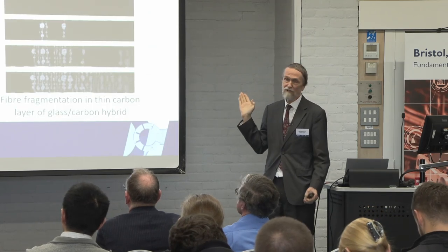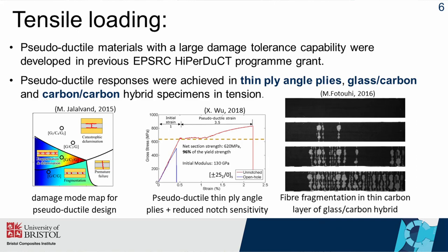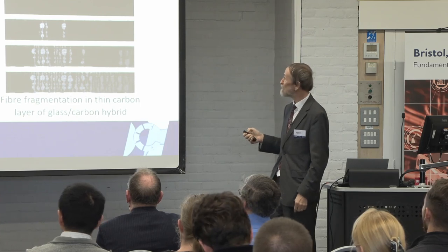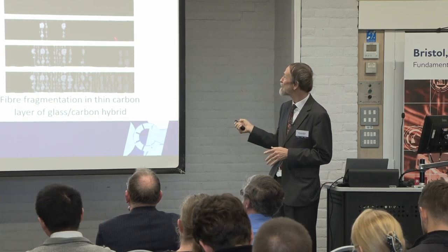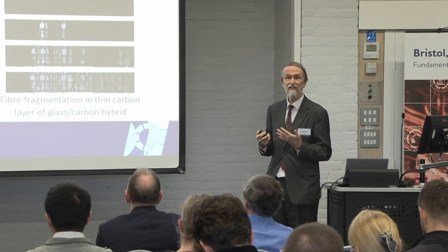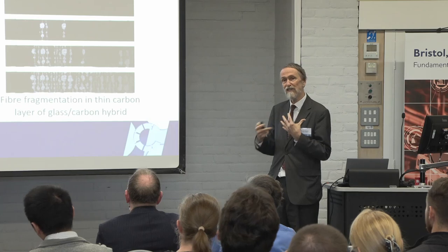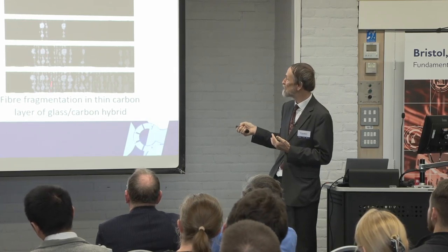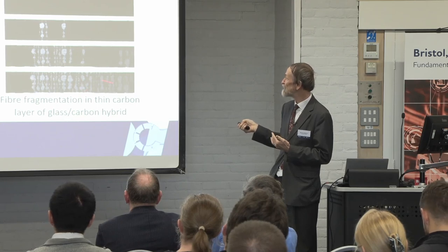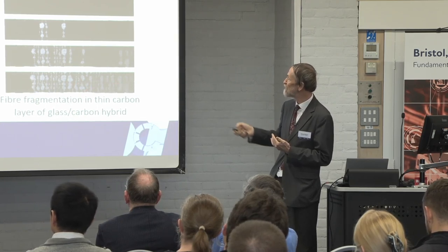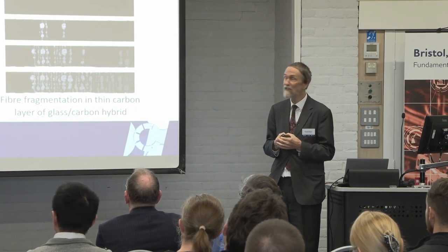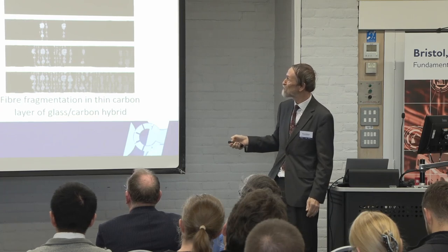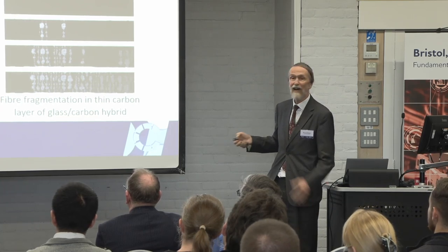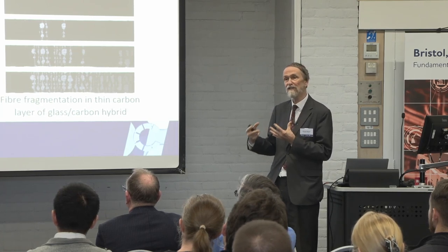So for tensile loading, a lot of this work came out of a big program grant we had a couple of years back on HiPerDuCT, high-performance ductile composites, where we showed we can get a very nice pseudo-ductile response in tension by hybridizing materials. There's different ways that can be done. This over here shows what happens when we mix carbon and glass. And if we do it right, with the right combinations and the right architecture, we can get multiple fragmentation of the carbon. And this is still integral. And this gives us a stress strain curve with a plateau, which is very like the ductility you see in a metal. So we developed maps to be able to design these and to look at the different failure mechanisms and the different combination of properties so we can design it to get the response we want.